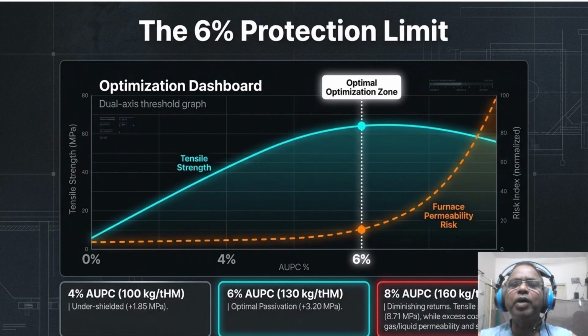But once you go past 6%, roughly 130 kg per ton hot metal of PCI, you hit diminishing returns. So tensile strength stalls out at 8.7 MPa. But look at that orange line. Your permeability risk skyrockets because excess coal starts choking the gas and liquid flow. 6% is our optimal zone. To keep this straight, let's look at the step-by-step sequence from the raceway to the hearth.